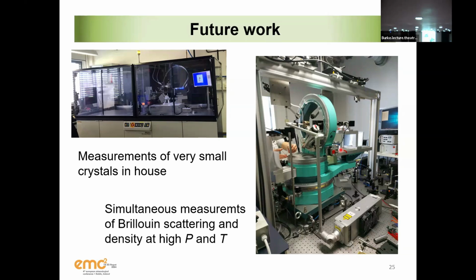With CO2, Alex tried something in collaboration with somebody from Oxford, and they succeeded to heat to 1,400 K at 17 GPa, and it was in helium. I don't know if it's a lucky thing because he did it once. No, he did it 3 times, and it didn't break. So the fact is that, I don't know, Leonid will say, no way, no helium. We need helium, so we do it.